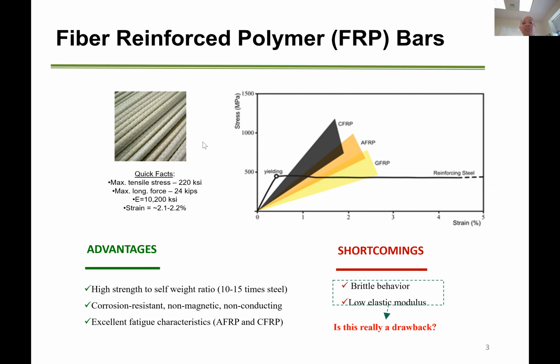So if we look just in the quick facts comparably to these bars on average, we're looking at strengths up to about 220 KSI, very similar to what we're seeing in steel pre-stressing tendons. But as we see here, perhaps some people think it's really a drawback to have this lower elastic modulus of about 10,000 KSI, but is that enough for what we need when we're designing?